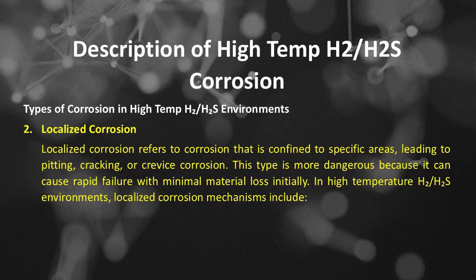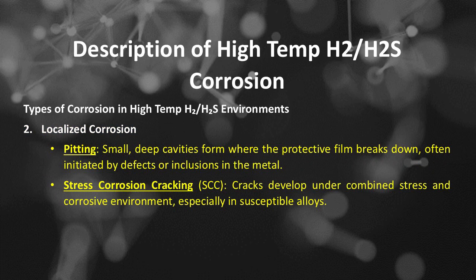Type number 2 is localized corrosion. Localized corrosion refers to corrosion that is confined to specific areas, leading to pitting, cracking, or crevice corrosion. This type is more dangerous because it can cause rapid failure with minimal material loss initially. In high-temperature hydrogen or H2 and hydrogen sulfide or H₂S environments, localized corrosion mechanisms include pitting: small, deep cavities form where the protective film breaks down, often initiated by defects or inclusions in the metal.